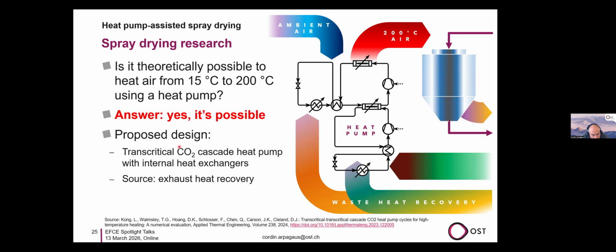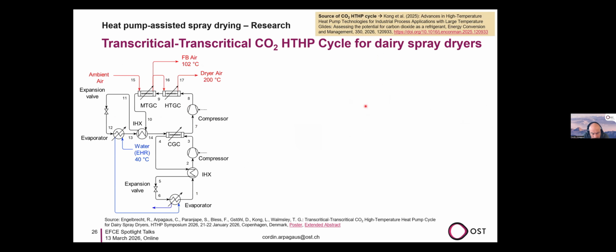And the proposal is to use a transcritical CO2 cascade heat pump with an internal heat exchanger. And here you see the cycle. This cycle has been evaluated by the colleagues from Waikato University in New Zealand, Lana Kong and Tim Walmsley. And they show that this system could work with CO2 compressors that are available today with 150 bar discharge pressure. And so 200 degrees can be reached. Okay, it's a theoretical study, but we also did the model of this heat pump cycle.